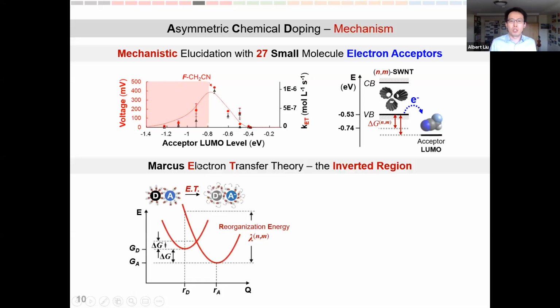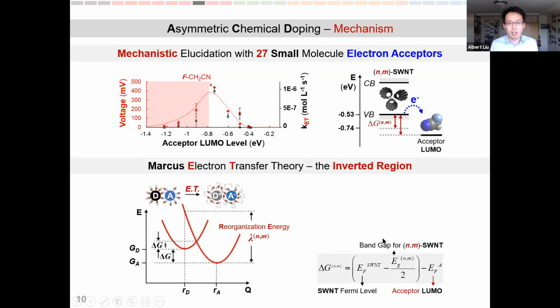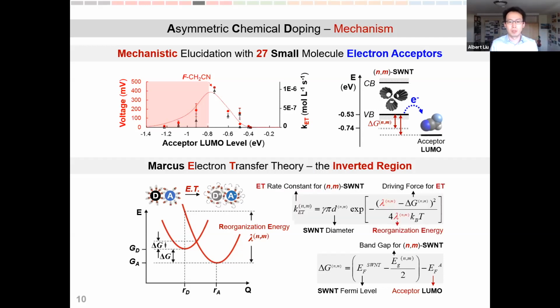In order to answer this, we go to the Marcus electron transfer theory, where for a donor to transfer its electron to an acceptor, this rate of electron transfer is not only governed by the thermodynamic driving force shown here as delta G, which can be calculated very easily. In turn, the other factor that governs this electron transfer rate is called reorganization energy, which is the Gibbs free energy it takes for solvent molecules to reorganize themselves around the donor-acceptor pair in order to facilitate this electron transfer. So this k_ET, or electron transfer rate, is maximized when delta G, or your thermodynamic driving force, equals this reorganization energy. As you can see, the Marcus theory can beautifully explain our experimental data.